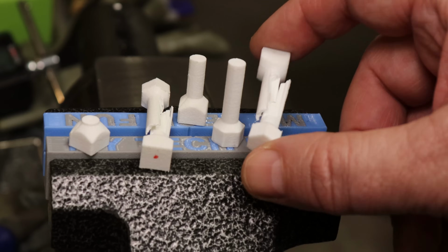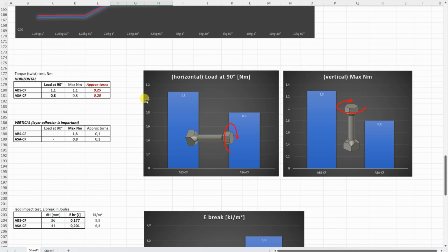the weaker layer adhesion. On torque or twist test, this is the load at 90-degree rotation with the horizontally printed test object, and here the ABS was noticeably stronger compared to the ASA, and similar ratio we have with the vertically printed test objects where the layer adhesion is important, but it is interesting to notice that the numbers are similar with the horizontally and vertically printed test objects because they have the same dimensions.